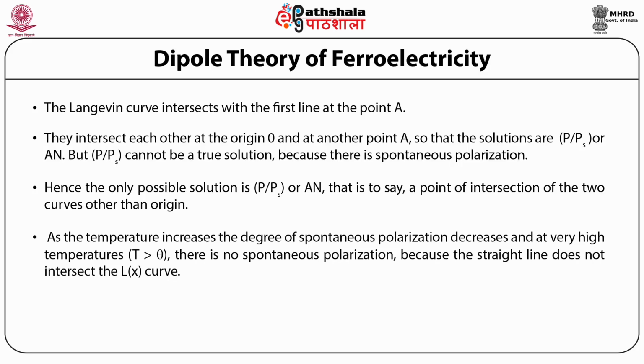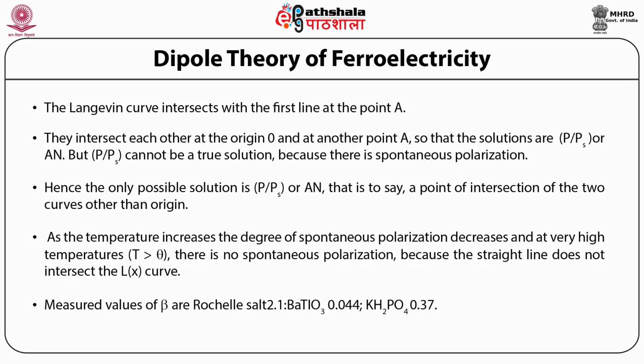As the temperature increases, the degree of spontaneous polarization decreases, and at very high temperature, T greater than theta, there is no spontaneous polarization because the straight line does not intersect the L(x) curve. Measured values of beta for Rochelle salt are 2.1, BaTiO3 is 0.044 and KH2PO4 is 0.37.